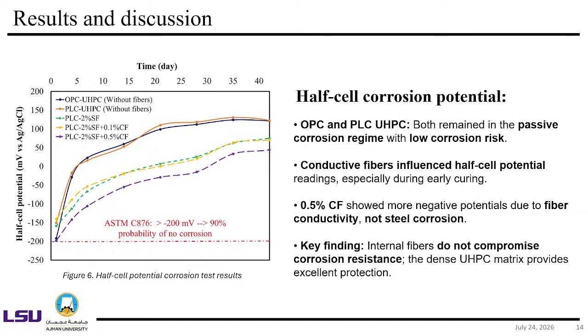This is the last test, which is the half-cell corrosion potential. From the top to bottom, the top ones, which are the best performing, are the OPC and PLC ultra-high performance concrete without any fibers. These two middle ones are with 2% steel fiber and just a little bit of carbon fiber. The lowest one is this. Of course, the more carbon fiber, the lower it is. However, it has not compromised the corrosion resistance. It shows more negative values because of the conductivity, because it is more conductive, not because of steel corrosion.